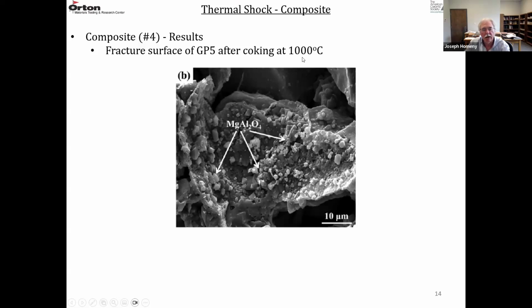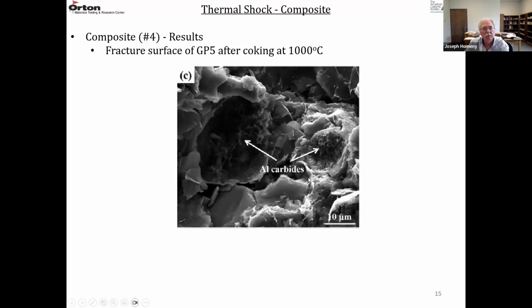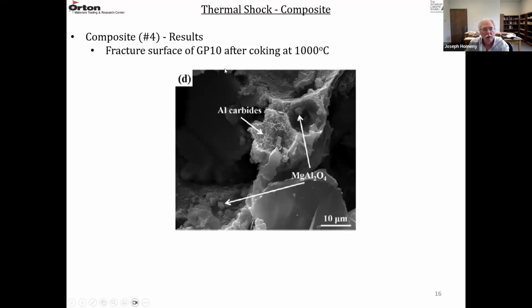This is GP5 after coking at 1,000 degrees C. And all these small crystals are spinel crystals, MgAl2O4, forming on MgO aggregates. And this is another one of GP5 after coking at 1,000 degrees C, showing the aluminum carbide formation. And then GP10, which had a higher content of these MgO carbon pellets. This is coked at 1,000. You can see the needle-like structure of the carbides more clearly here. And then these blocky type crystals are the spinels.